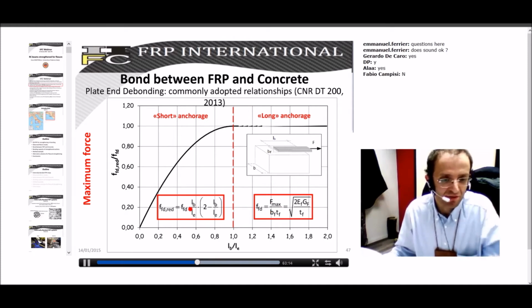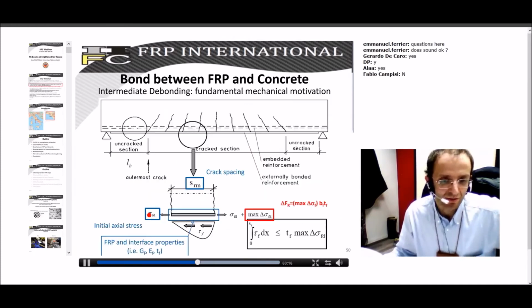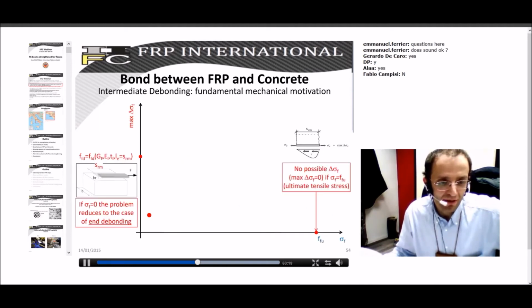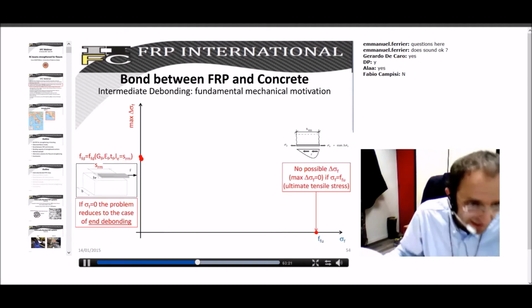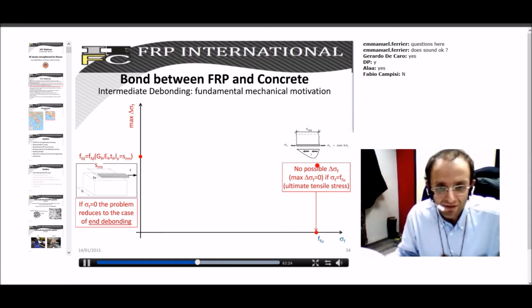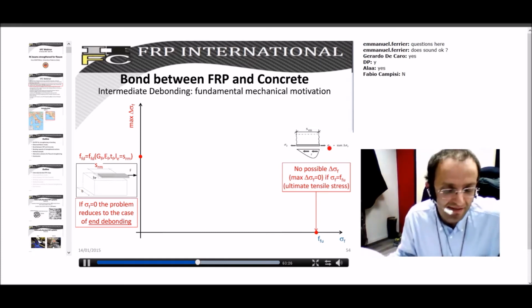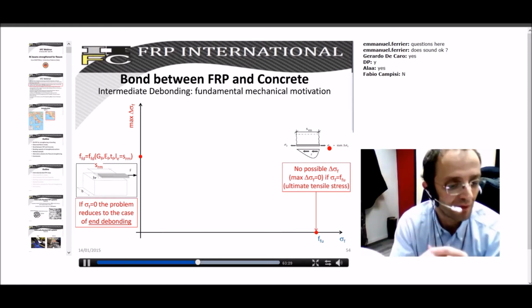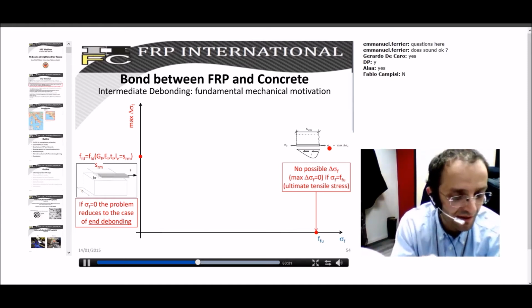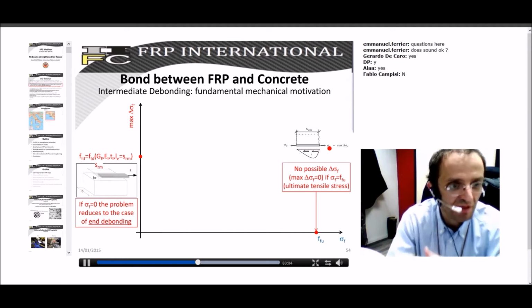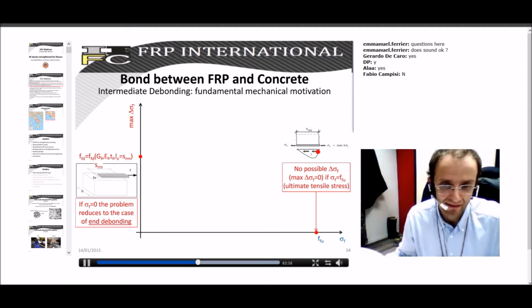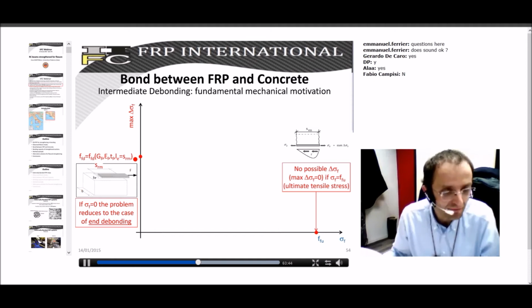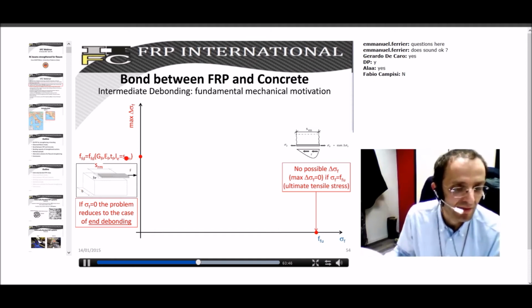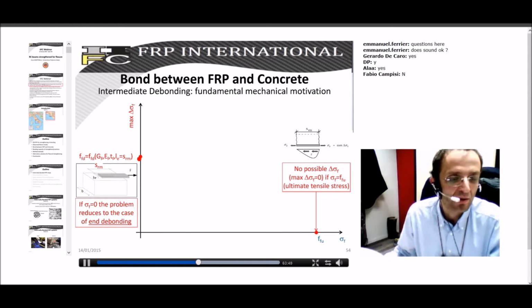But this is something which can be easily evaluated. So basically, the point you have here is the expression I've just shown you. You can easily evaluate it. So if you have sigma f here, the delta sigma is the maximum stress which can be applied and which results in debonding. This can be the square root of twice GF, EF divided by TF, or a lower value depending on SRM. If SRM is lower than LE, you have to reduce it.